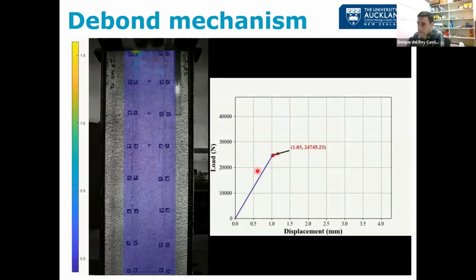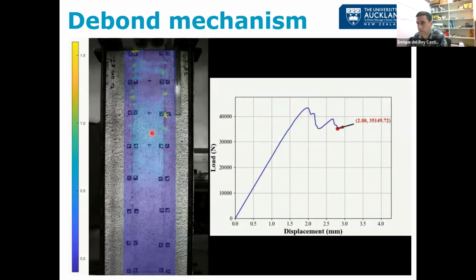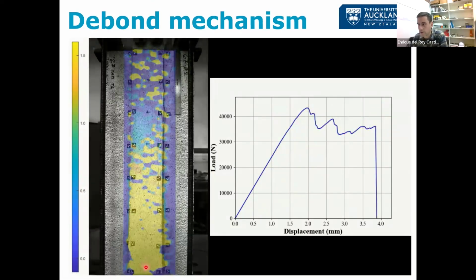So we have a very stiff initial loading, and then the FRP is debonding, and the debond progresses down, the strain progresses down. This one has no anchors. So when the debond line moves from there all the way down, the debonding is progressing. Now, what this is telling us a few things.